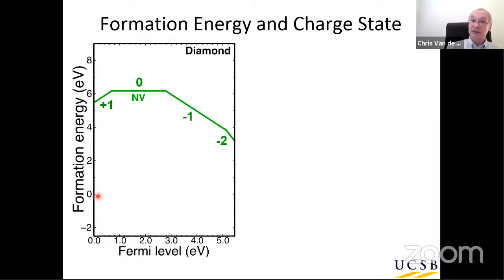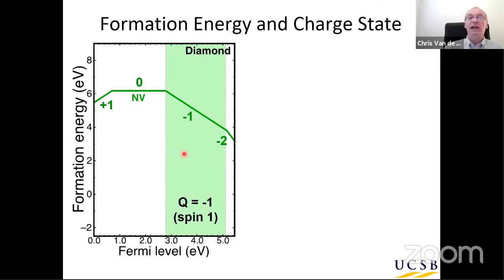On the left-hand side, we would have P-type material, acceptor doped material. On the right-hand side, we would have N-type material, donor doped material. So as I was saying earlier, to get the optimal spin state of the NV center, we want to be in the -1 charge state. Now, in general, it is actually not so straightforward in a semiconductor or insulator to select Fermi level positions that lie within a certain range within the band gap. It is relatively easy to dope the material fully P-type, with the Fermi level close to the valence band, or fully N-type, with the Fermi level close to the conduction band, but intermediate Fermi levels can be difficult to achieve.